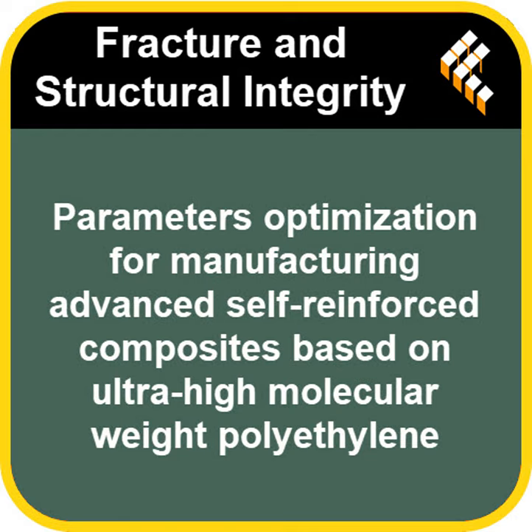Right. The fibers are great in tension, but the compressive strength of composites like this is usually limited by other factors, like the fibers potentially buckling, or the strength of the matrix material between them, especially under shear stress. Ah, so the matrix part, the bit that melted and fused, isn't as strong in compression as the fibers are in tension. Exactly. That partially melted matrix is more isotropic, less perfectly crystalline. Its compressive strength just can't match the incredible tensile strength of the oriented fiber core. So the material gives way sooner under bending loads, which involve compression, than it does under pure tension.